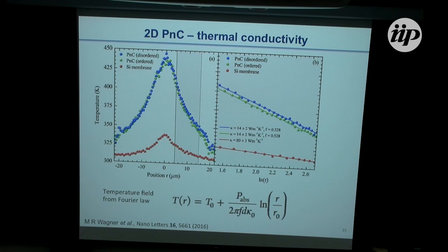To measure the thermal conductivity of these samples, we use a laser Raman thermometer, as I mentioned, and what we obtain are temperature maps ranging from the center, where the laser is, radially away from this point. The temperature is obtained from the shift of an optical phonon that we track that has been suitably calibrated. We use this expression to obtain the thermal conductivity from the temperature fields, and from the slope we obtain the thermal conductivity. Key parameter here is the power absorbed.